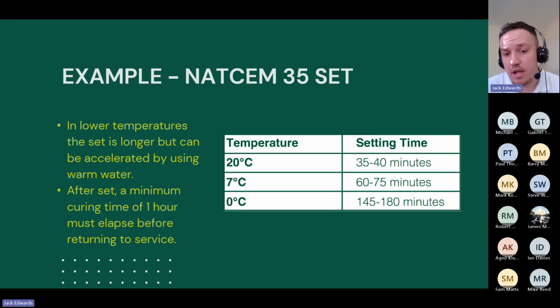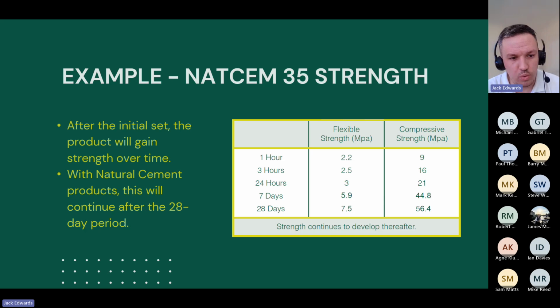So the curing period plus setting time at 20 degrees, for instance, would be an hour and 40 minutes, whereas at 0 degrees, you're looking at 4 hours. It's not very often that the product will be returned to service within an hour after it's been installed anyway, because there are other processes that need to take place. You might need to clean everything down, might need to get all the machinery out of there. Generally speaking, it will be 24 hours later anyway. But as long as you follow these guidelines, it will ensure that we don't get any issues in terms of returning things to service too quickly.